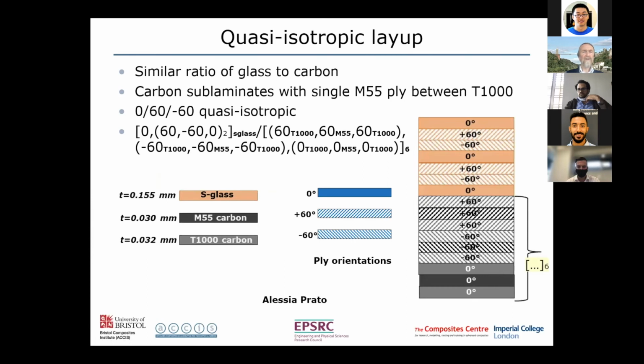So then we can do the same thing with a quasi-isotropic instead of a UD layup, and these specimens have a similar ratio of glass to carbon, and the carbon sublaminates are similar, not exactly the same as the ones in the previous picture I showed. In this case here, we just have a single M55 sandwiched between 2 T1000, and this laminate is repeated through the thickness. So we have a 0 plus minus 60, 0 S-glass, and then we have 60-degree ply with T1000, M55, T1000, then a -60, and then a 0, and that's repeated 6 times through the layup.